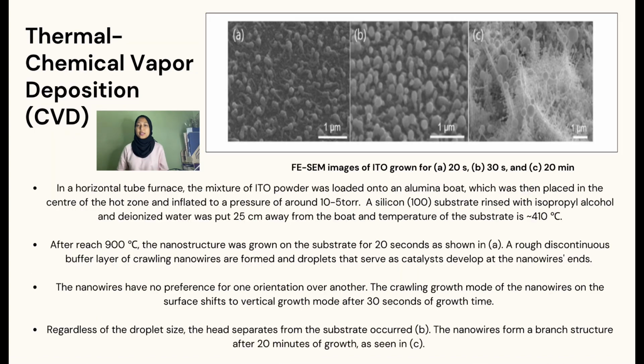This figure represents the ITO growth by CVD. At 900 degrees Celsius, the nanostructure was grown on the substrate for 20 seconds, as shown in figure A. We can see that a rough, discontinuous buffer layer of crawling nanowires is formed, and droplets that serve as catalysts develop at the nanowire ends.